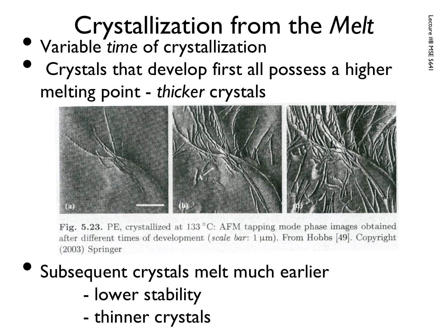And so AFM looks at the resistance to this nanoneedle as it pokes on the surface. The nanoneedle can detect the crystals that form because they're harder. So it sees a different modulus when it taps across the crystal versus when it taps across an amorphous content. All right, so these images are showing you that feedback from the AFM as it taps across the surface. It sounds really crude, but it actually works pretty darn well, especially in this experiment.